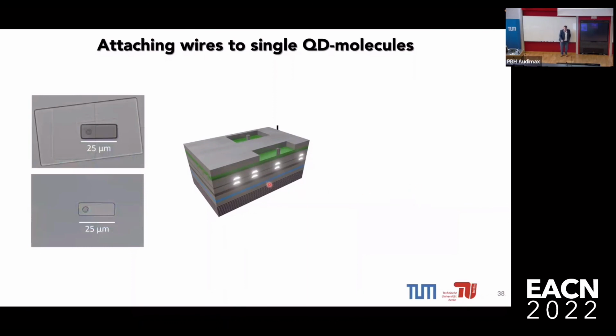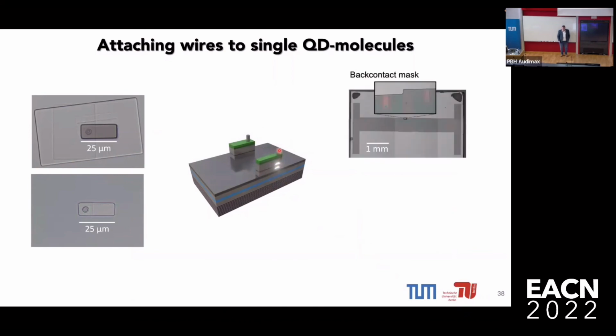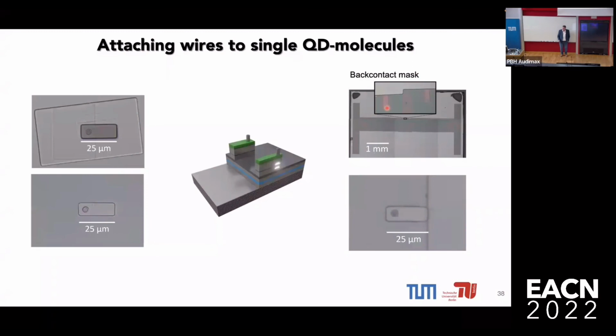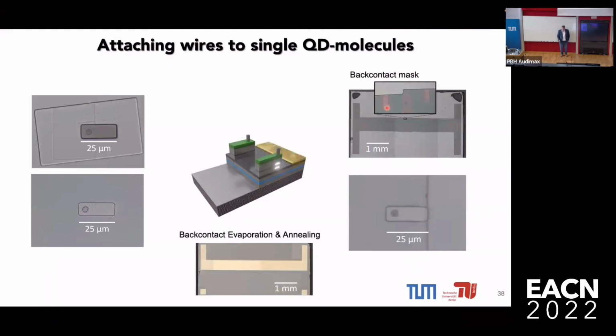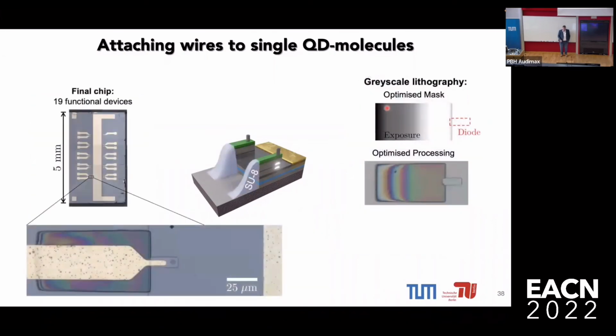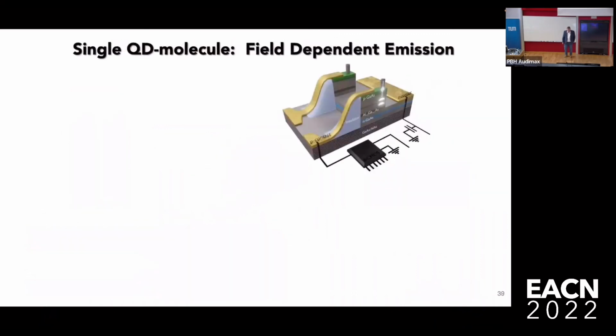He sends it then to Munich. So I've added our logo down here at the bottom. And what we do is we then etch down to make a device which contains just a single molecule with a little lens above it. There you see one of those. If you see these little rings here, each one of those has a single molecule underneath it. We then take that single molecule, process the diode, and we put contacts on one side of the PN junction. So what is the back contact? This is an insulator, and there's many of these individually contacted molecules. So you see a nice molecule that's this little annular contact. Each molecule is contacted by a one wire. That's what the device looks like.